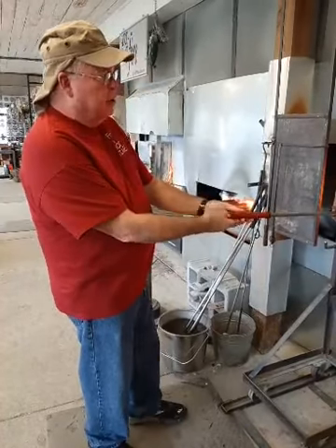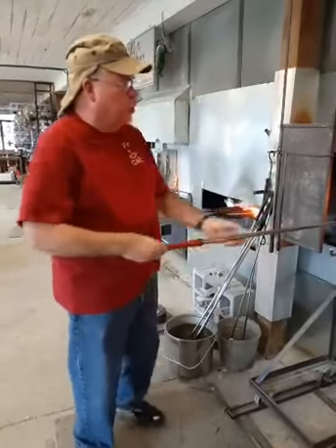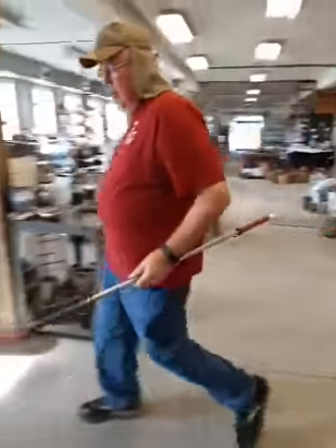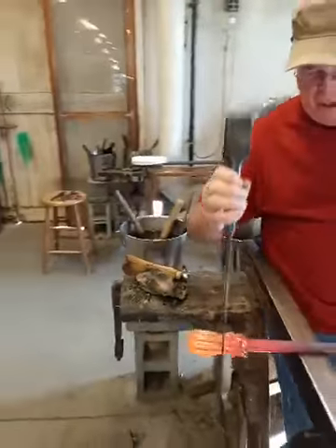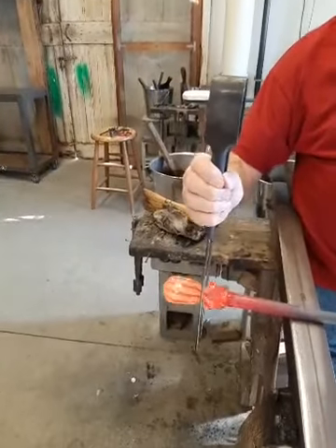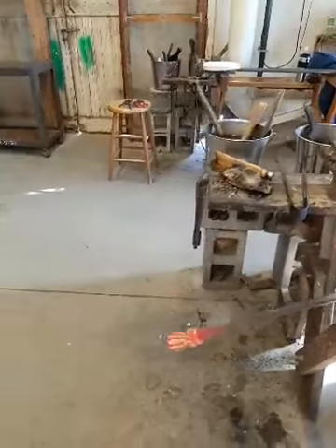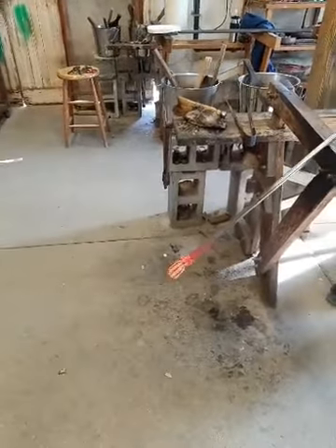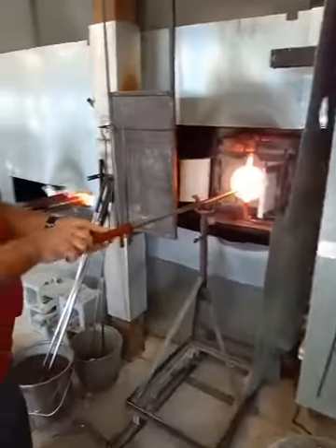So what I'm going to do now is go back to that jack line I cut, but I'm actually going to push it back toward the pipe a little bit to help it seal at the pipe where that separation, that V shape is. So by going right here and pushing back toward the pipe a little bit, that's going to make sure it's done. Now I'm going to see if it's closed at the other end. And it's not. There's probably an opening on that end. Yep. Someplace. That's where we cut it. So, we'll go ahead and close it up.